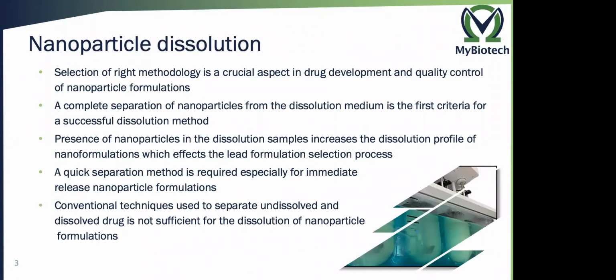What we have seen over the years is that selection of the right methodology is crucial for drug development, and afterwards for the quality control of nanoparticle formulations. Once you are done with development and technology transfer and bring your nanoparticles to market, you need a dissolution quality control method that can differentiate between bad and good formulations. The first, very important criterion is the separation of nanoparticles from the dissolution medium. When you take your sample, if you cannot separate the nanoparticles, they all go into the HPLC analysis together and dissolve in the HPLC column, and at the end you have a higher dissolution profile than the real profile.